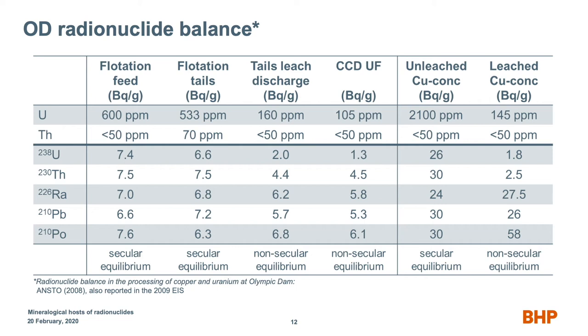We take that material and we float it and we make a float tail. The numbers change a little bit because some of the uranium gets recovered to concentrate, but very roughly these numbers are about the same, so flotation tailings does not do anything to that radionuclide distribution. Then we go into tails leach, and first thing in tails leach, we're dissolving the uranium, we dissolve some of the thorium, we take out a little tiny bit of those radionuclides, not a lot. We won't worry about CCDs.